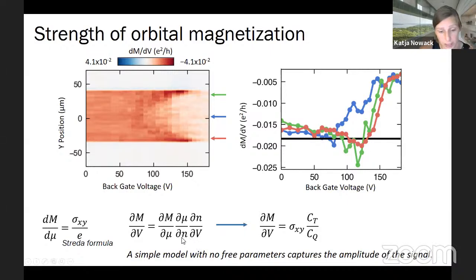And this we can actually measure, at least in a bulk fashion, by doing electric field penetration depth measurements on the samples, which we have done at the same time. And these give you direct access to the ratio of the top gate capacitance and the quantum capacitance of your device. And so we can compare our data to sigma xy, which we measure, and then multiply that with the capacitance ratio that we actually measure. And this gives us this black line here. So this gives us an order of magnitude that we should expect for dM/dV.